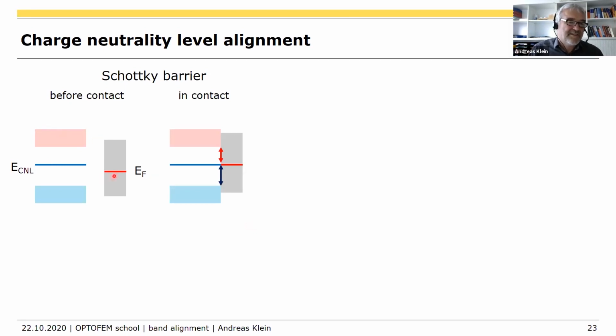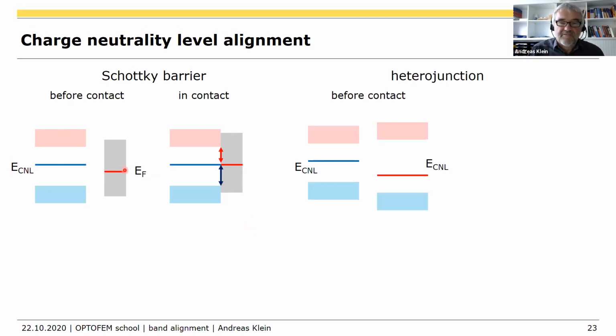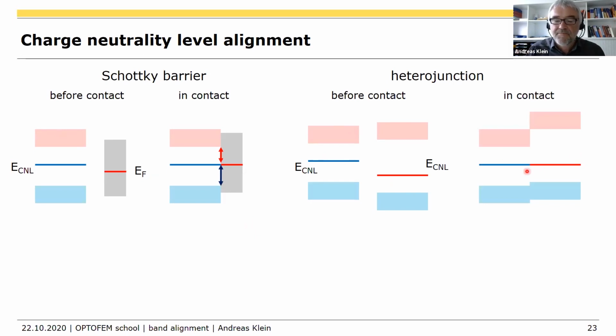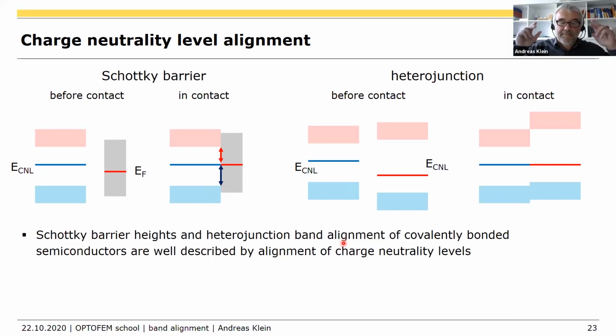Well, in a metal, the charge neutrality level is, of course, the Fermi energy. And if you have two semiconductors, you can get the alignment of the charge neutrality level as well. So these charge neutrality levels, although I explained it for the surface, we have to look at the charge neutrality level of our induced gap states. And these induced gap states are related to the solution of the Schrödinger equation of the bulk material, those with the imaginary K. So the charge neutrality level is a bulk property of the semiconductor. It's not an interface property. In the bulk, we don't need to care about it. We only need to care about these charge neutrality levels at the interface. But it's a property which is determined by the bulk of the material and not by the interface itself. So that means we can draw the charge neutrality level everywhere.